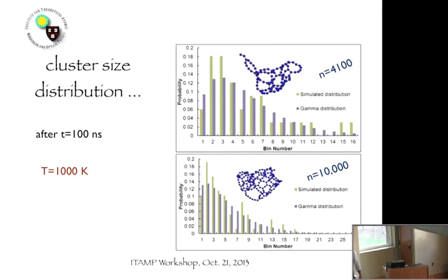So the one take-home message from all this, which I think has also been discussed, is that at very low temperatures and low densities, if you start with the so-called bottom-up approach, you almost have no hope of forming curvature, no hope of forming larger structures. What you would get would be long chains of carbon atoms or carbon-hydrogen bonds.